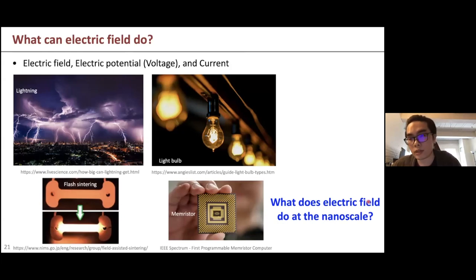One is flash sintering. Basically, you have something you want to sinter, but other than just raising it to high temperature or applying stress, you pass through current, or you apply a very large voltage, and then you can sinter your material at much lower temperature and in a much shorter time. And memristive devices, as I mentioned, are emerging, or now are actually already very popular among a lot of groups, and they are a storage device that you can use for neuromorphic computing. So the question is, what does electric field actually do at the nanoscale?